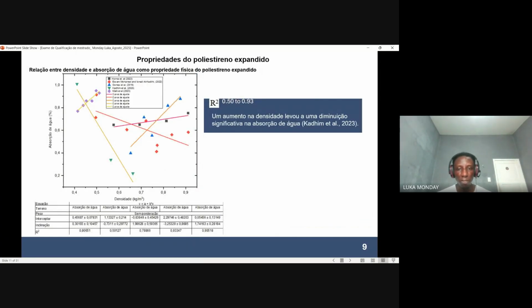From the physical properties, some key aspects were abstracted from the literature, which are the density and the water absorption, to check the correlation between these two properties. What is the relationship between density and water absorption with respect to expanded polystyrene being used as a thermal insulation mortar? From the linear regression analysis, an R-square of 0.50 to 0.93 was obtained, which clearly shows a relationship between the two properties, density and water absorption. Yes, density clearly plays a key part with respect to water absorption based on the linear regression analysis as utilized in respect to expanded polystyrene.